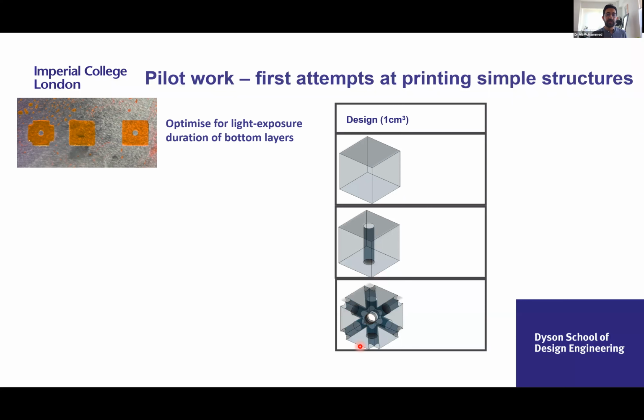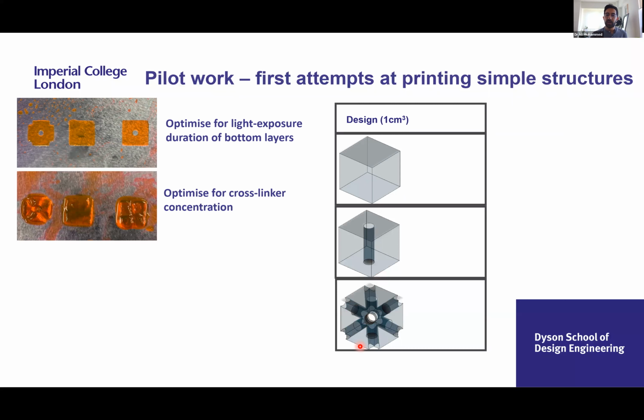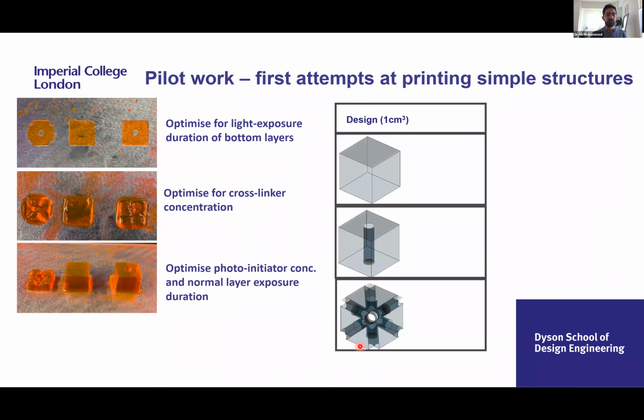So we optimized the light exposure during the bottom layers. The bottom layers are the ones that have to really attach to the build platform. We saw some success there. However, the print continued to fail. So we optimized the cross-linker concentrations to give it a bit of a boost, so that the material was a little bit more solid. As you can see there, it's quite gel-like. We reached a very good point where the structures were 80 or 90% successful. However, we saw that a lot of it was still failing.